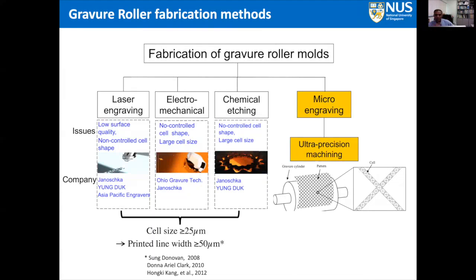And when you have a 50 micron thick wire on a transparent surface, you see that the transparency decreases significantly. So our aim is to reduce the width of these cell sizes, and therefore we can in turn reduce the printed line width as well.